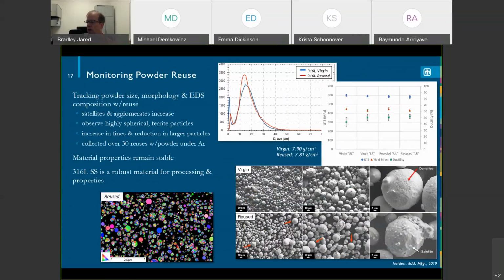So we've been monitoring the powder now in our machine. The previous slide was for parts we got from a vendor. This is now a Sandia material that we're processing and characterizing with every build. One thing we found in 316, it's fairly robust, right? So now we understand if we reuse the powder, we're getting properties, we can see some of the very minor trends. But it's really important for us to track this. So every time we build a part now, we sample powder and we capture that. And so now we know sort of how often we can reuse the powder and the reliability that will give to us.